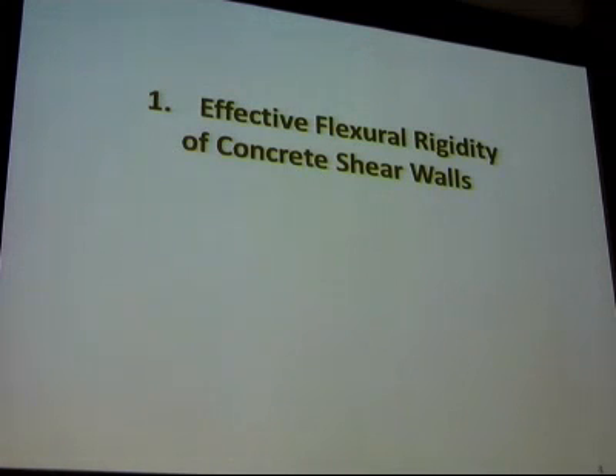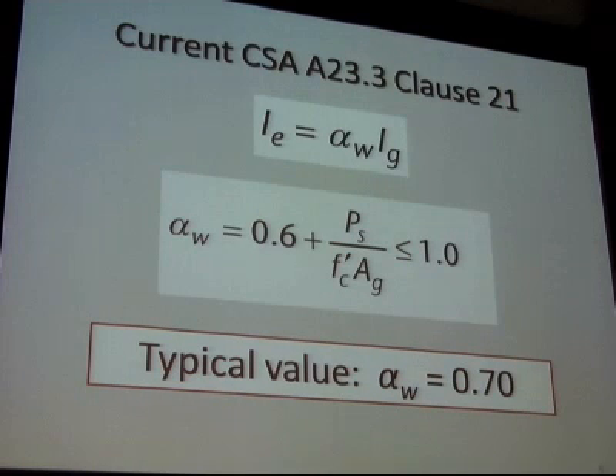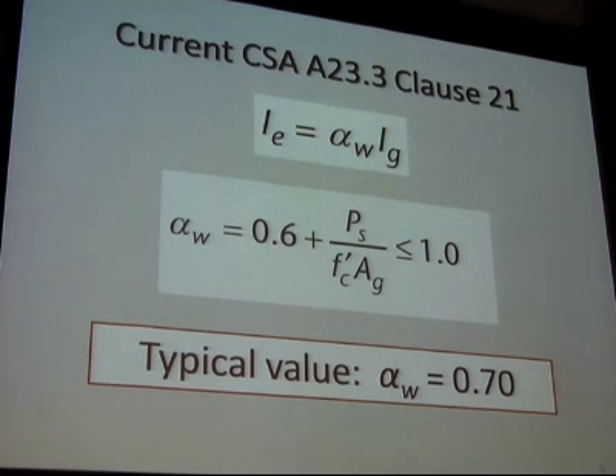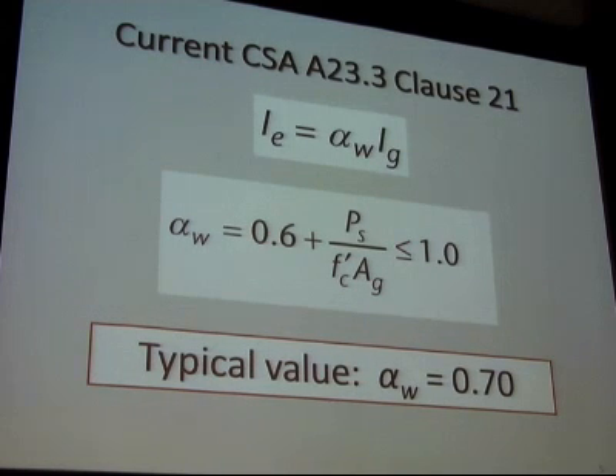First of all, our code is going more and more towards displacement-based design for concrete shear walls, and therefore you need to estimate what your displacement demands are. And to do that, typically we use a linear dynamic analysis, and we need to use an appropriate flexural rigidity to account for cracking. And this is an expression that's been around for a long time. And when I first looked at this subject, I thought it was a great expression. Actually, Tom Paulay came up with it. And it's currently used to analyze buildings and to estimate displacements.